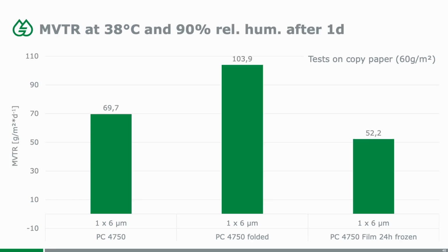If we then go and look at MVTR, and in this case we will again focus on tropical conditions because that's the most harsh test that you can think of. On the left hand side you've got the comparative data of PC4750 on copy paper without any mechanical stress. It's around 70 MVTR. Then if you fold it, you see that there is an increase in the moisture vapor transmission, which might be due to some micro cracking.